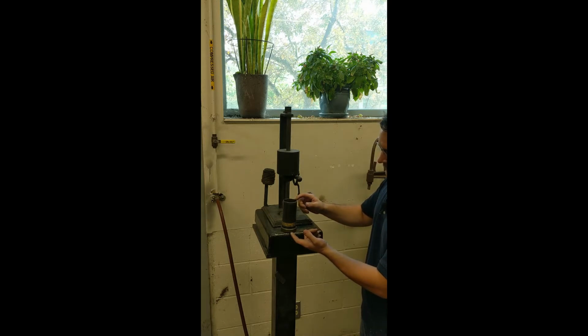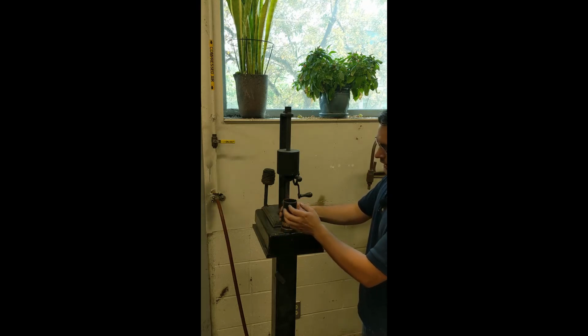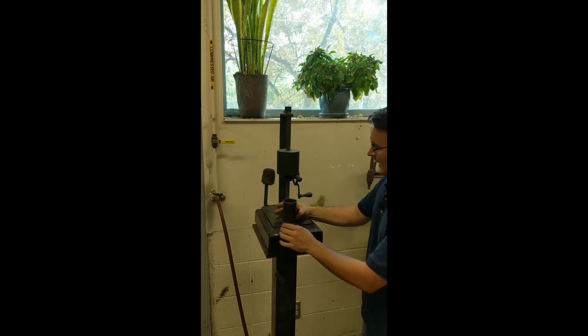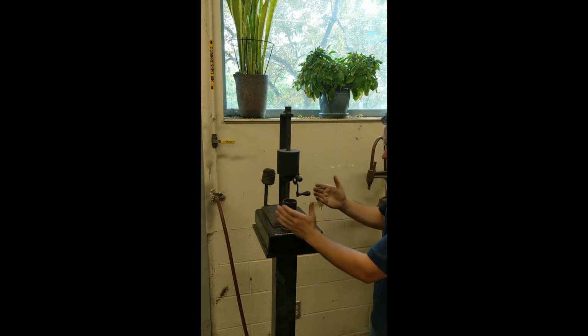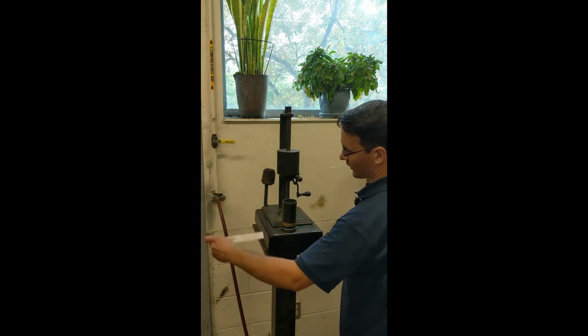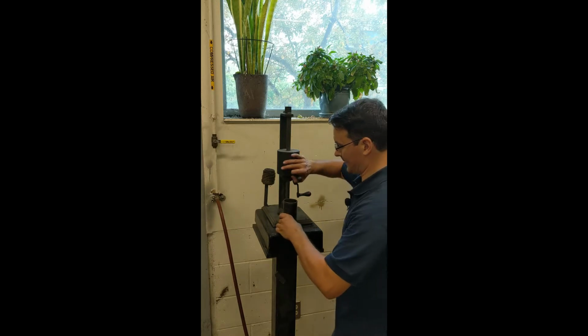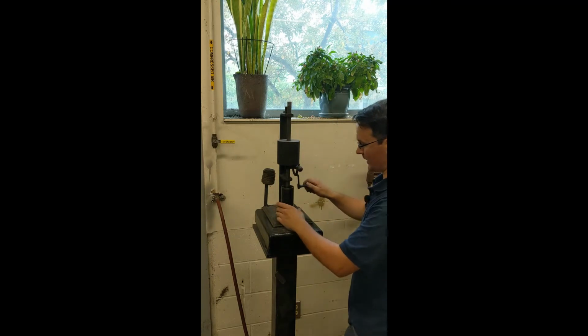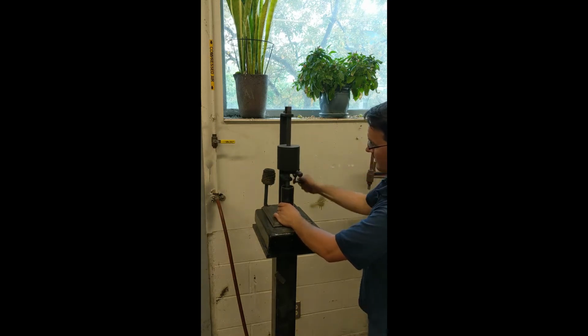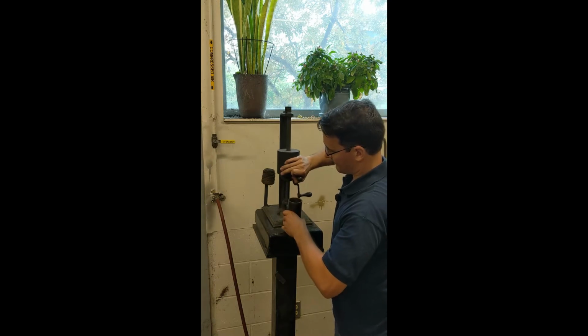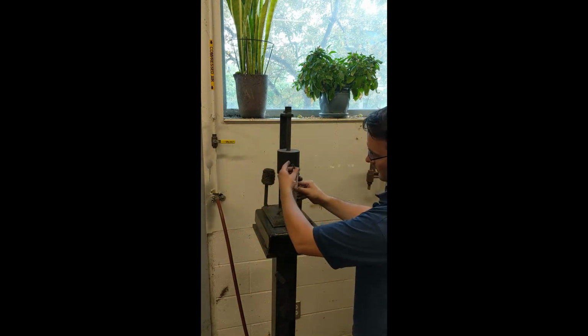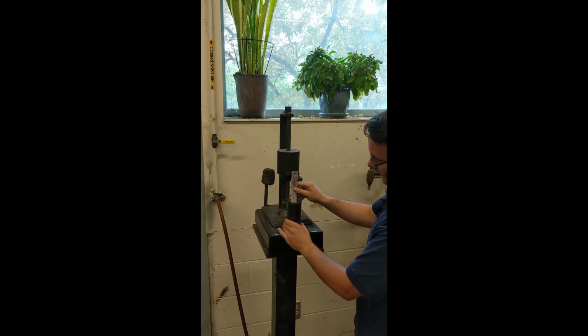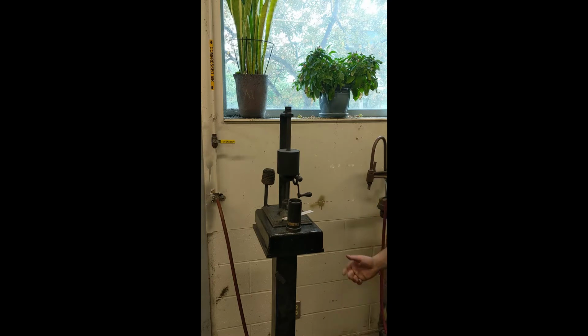I have a standard specimen tube here, a hollow tube filled with loose, uniformly graded sand just out of our muller. And this hammer is going to compress the sand, and then using this ruler, we'll get a percent compactability. So I'll load this in place. Three rotations of the hammer. And then we can put our ruler in here and see that this is about a 46% compactability. That means that to fill a given volume of our flask, we need to have prepared more than double that volume of loose, uncompacted sand.